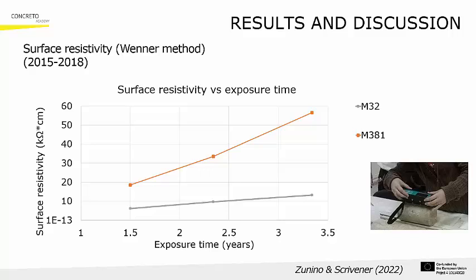In terms of time evolution, OPC concrete shows a slight increase in resistivity, likely due to the ongoing reactions in this highly humid environment. For LC3 concrete, a steady increase over time is observed, indicating that the synergistic reactions are still ongoing, at least after 3 years of exposure. These results are consistent with findings by Zunino and Scrivener from 2022.